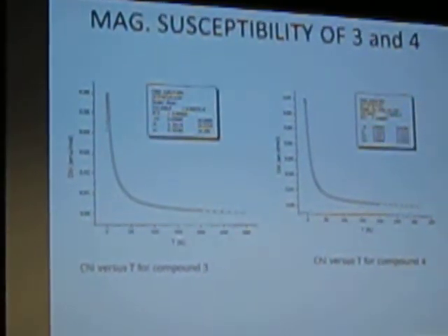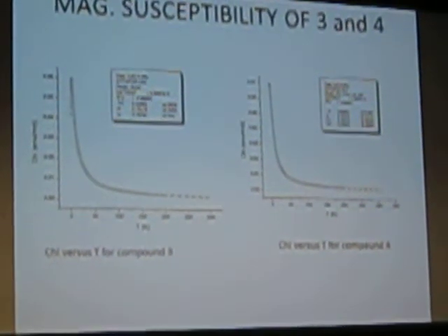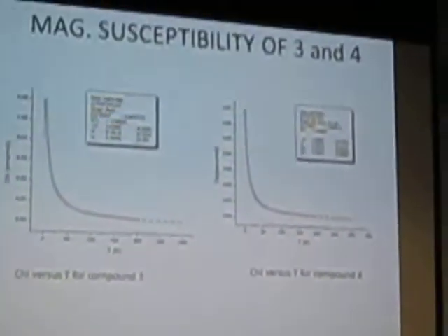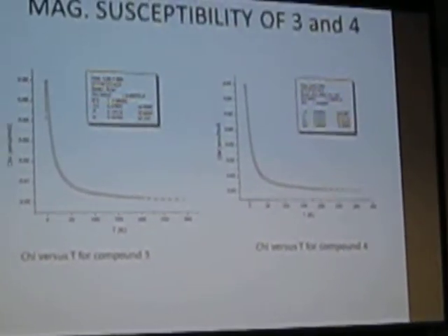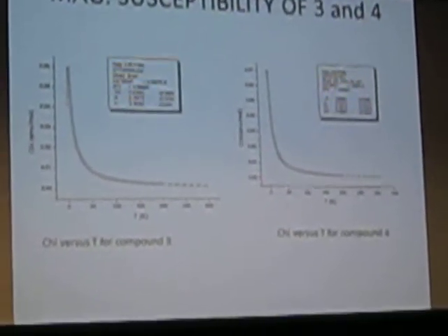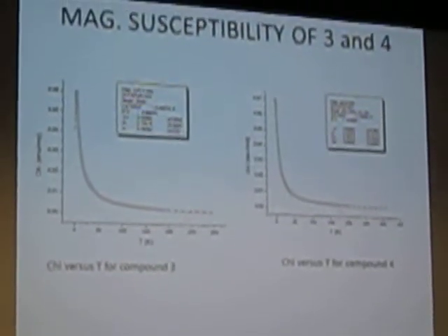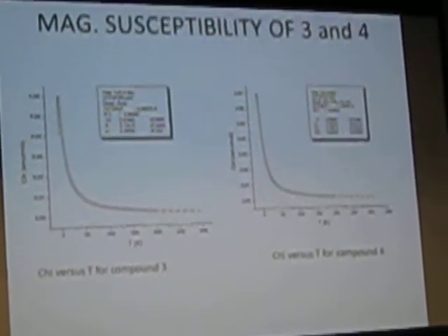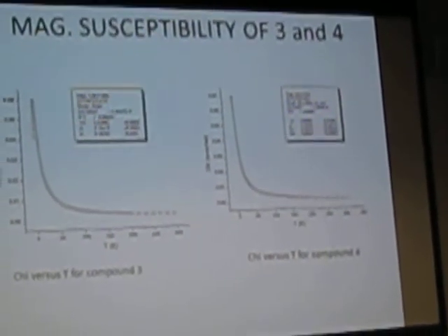Okay, so what is the magnetic susceptibility data? Why don't I have any X-ray crystallographic structure information on this? Well, there are a lot of problems with the crystal structures, or with the collection of the data. Actually, both of the materials are not single crystals. In the case of compound 3, there's actually significant twinning occurring in the compound. So there's actually 3 components in one single crystal.